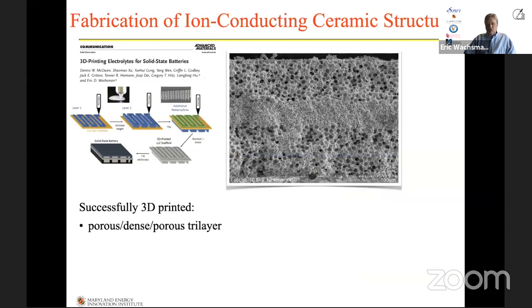This is one, this is what we call a tri-layer. It has a porous, dense, and porous layered structure. What we're doing in our batteries is we're filling the porous structure with the electrode materials, lithium metal on one side and whatever the cathode may be on the other. And you want that separator layer to be dense to prevent the shorts between the two different layers.